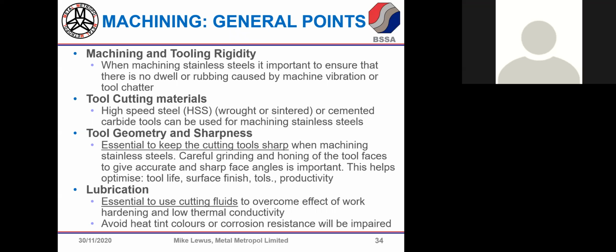Now, I'm familiar with tap testing, where you can look at the whole frequency dynamics of the tool, the workpiece and the machine and see where you've got a frequency response that minimizes vibration. I mention it mainly because it's quite counterintuitive. Usually if there's vibration and chatter on a machine, say a turning machine, people immediately want to slow down or cut down all the parameters, you know, lower the depth of cut, lower the feed, lower the revolutions on the turning part. But sometimes actually you'll find there's less vibration, you'll find there's lobes of lower frequency response at higher parameters. So it's just worth being aware of that.